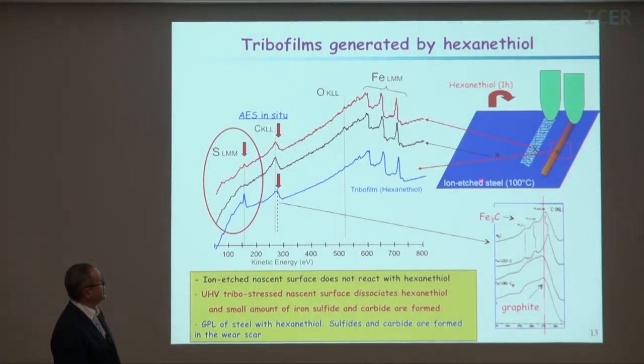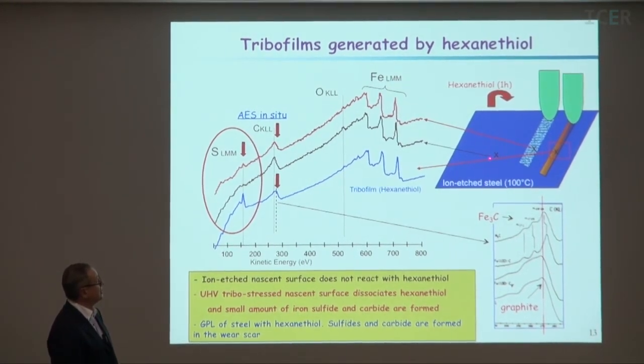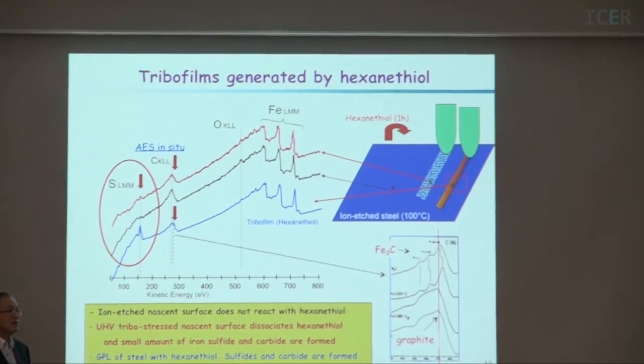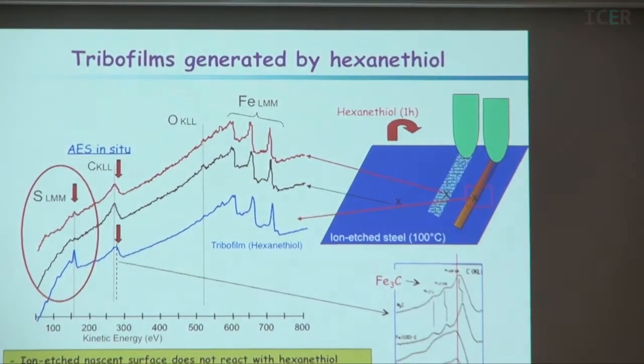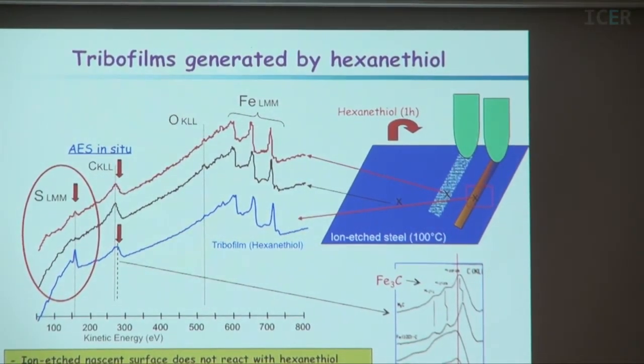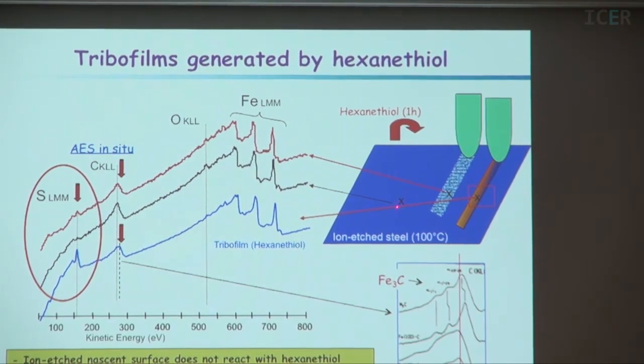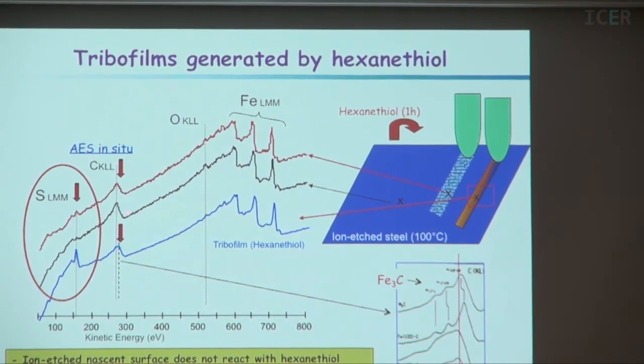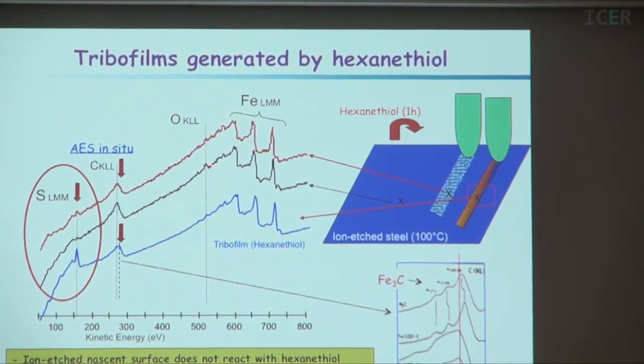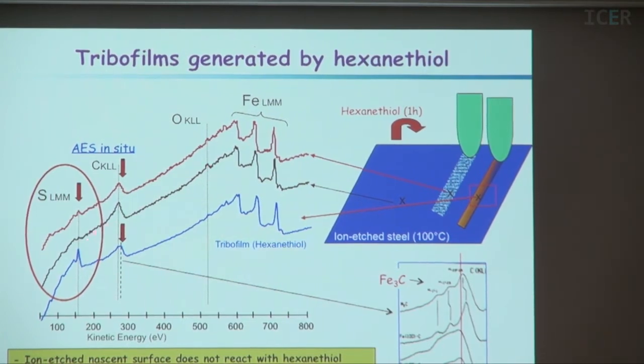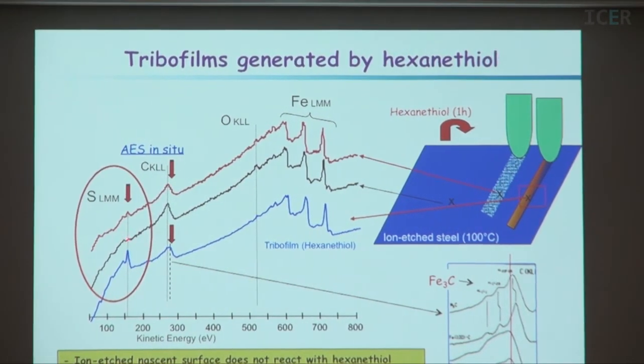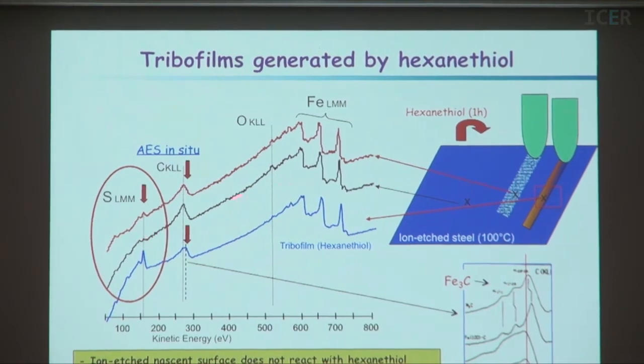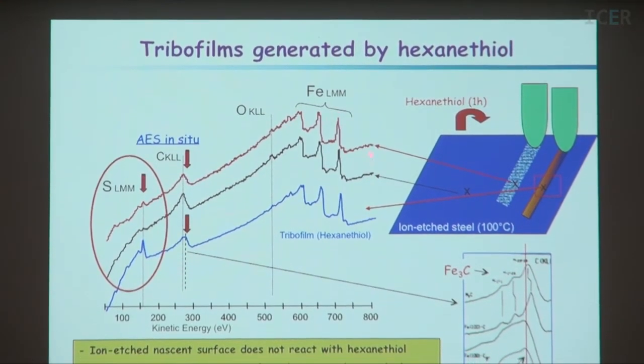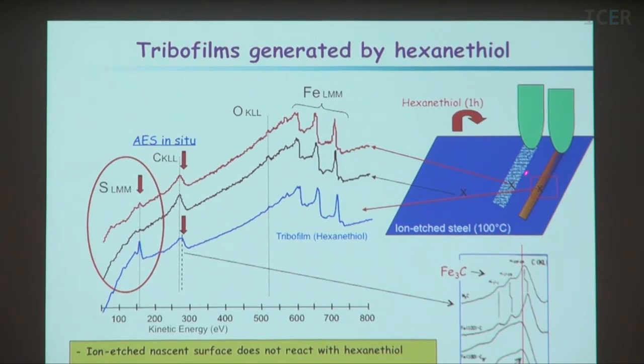Here, you have the surface after the test. So this blue area is an ion-etched surface. The oxide has been removed. So if you look at the analysis here, this is the Auger spectrum. You see only iron and a little bit of carbon contamination. Oxygen is very small. Practically no reaction with the sulfide. If you look at this red spectrum, we come from here.